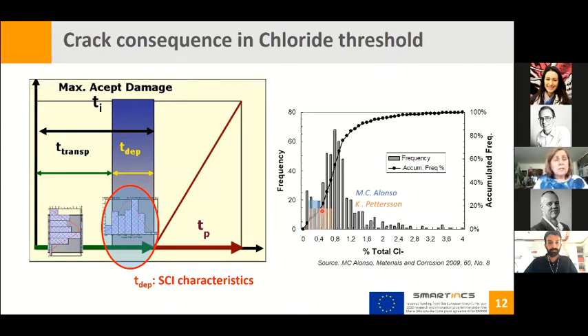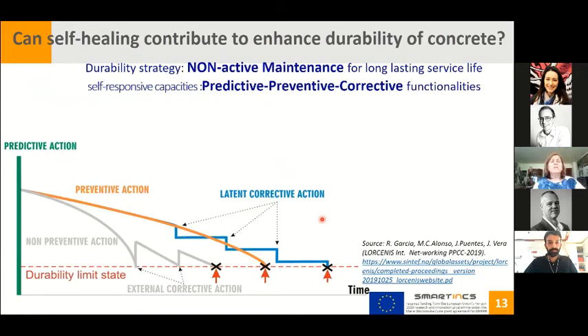So when analyzing the service life of cracked structures, we need to think that there is not only a higher transport of the chloride, but also a decrease in the chloride threshold. As I mentioned before, the environment around the reinforcement in the crack is clearly changed, and can be the reason for the faster initiation. But now we need to comment on how self-healing can contribute to enhance the durability of concrete.